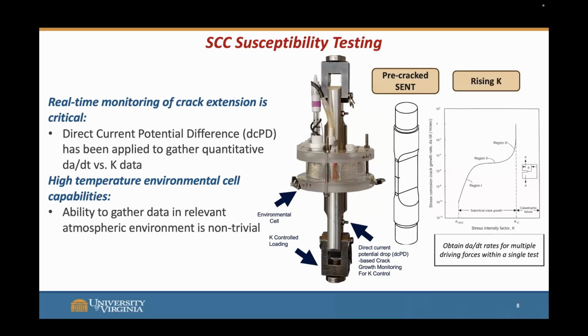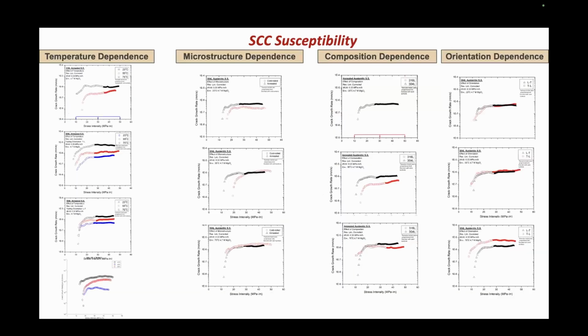Our testing. So we do real-time crack extension, DCPD specifically, and this allows us to measure the crack in situ and then allow for K testing. And so we do K-rise testing at a dK/dt of 0.33 MPa square root meter per hour. And then also along with this project, I created a high temperature environmental cell. So this allows us to do either full immersion or atmospheric conditions at anywhere from 23 C to 100 degrees C. And so that's kind of the overview.